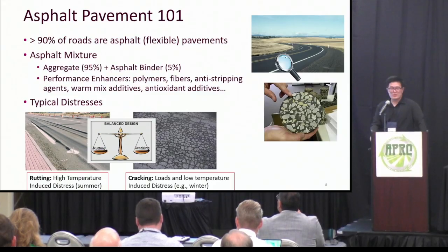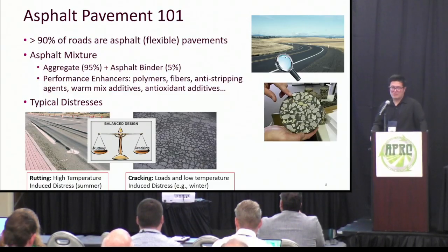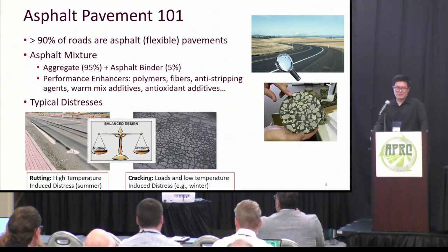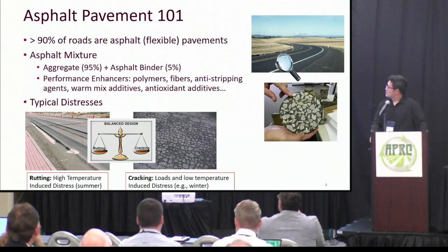If you are not very familiar with asphalt pavement or asphalt, here I have two slides to briefly talk about asphalt pavement. If you drive on the road, more than 90% of the time you drive on asphalt pavement. For an asphalt mixture or asphalt pavement, there are two components. One is called aggregate or rock, which is around 95% by weight. And then the second component is asphalt binder, which is roughly 5% by weight.